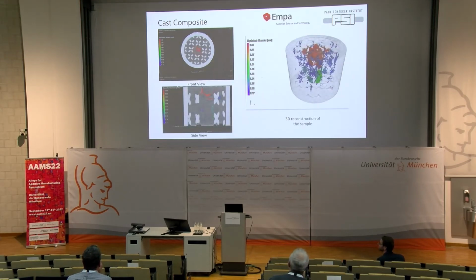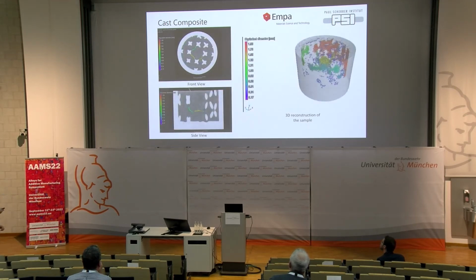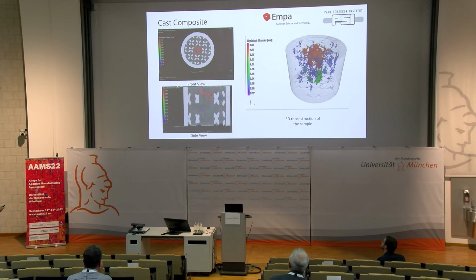Some problems are also detected when having a look at the upper part of the sample. So this one was the lower part, and this is the upper part of the sample. And again, the appearance of this porosity can be attributed to some geometrical configurations, as this is exactly the part that connects the hollow part of the cylinder with the lower part where we have the internal lattice. But in general, we can say that the interface between the steel and the copper is free of cracks, at least at the left and the right part. So the majority of the problems are focused on the central part of the structure.